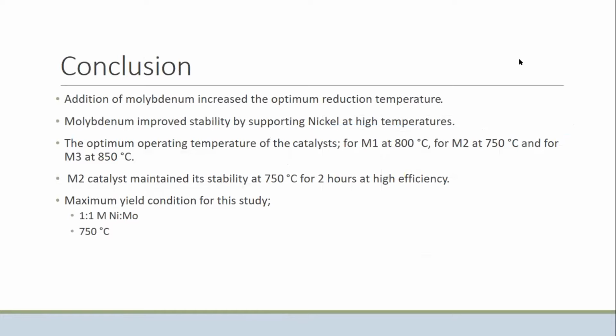To summarize this presentation, the addition of molybdenum increased the optimum reduction temperature, and also improved the stability by supporting the nickel at high temperatures. The optimum temperature of the catalyst for M1 is 800 degrees, for M2 750 degrees, and for M3 850 degrees. The M2 catalyst maintains its stability at 750 degrees for 2 hours at high efficiency. Also, an optimum molybdenum mixture with nickel can increase stability with high efficiency in the partial oxidation reaction. Also, we can specify that the maximum yield condition for this study is the 1 to 1 molar nickel to molybdenum mixture at 750 degrees.